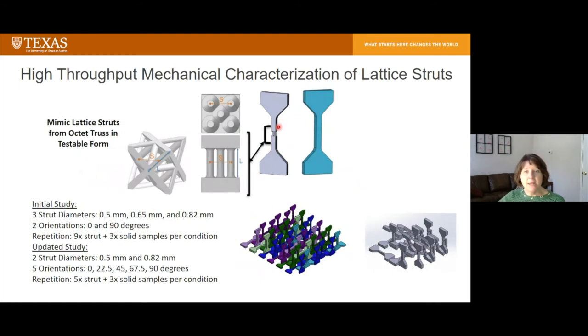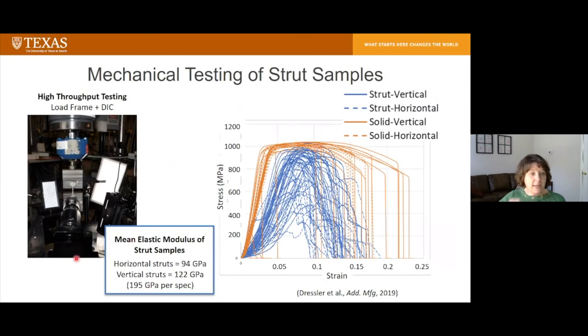One of the things we did is we created small tensile bars with the gauge length replaced by small sets of struts. And so that allowed us to build a whole bunch of struts at different orientations, flat or vertically, and with different sizes of struts, and to see what effective stiffness or modulus, tensile modulus, we got from the struts and whether that differed from what we got from the bulk material. We worked with Sandia National Labs to do this. This is a picture of their high throughput testing system that uses a load frame and a DIC system to rapidly test all of these samples. Some of the results you'll see here on the right, where the orange is the solid specimens, and then the blue are the strut specimens.